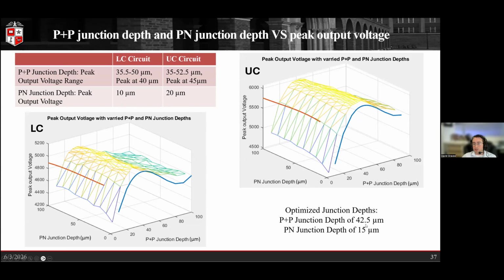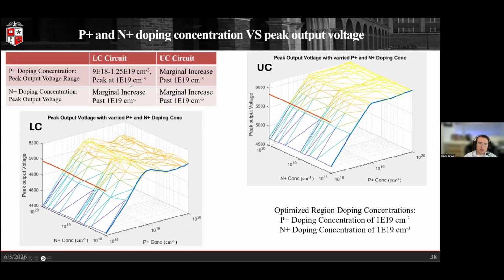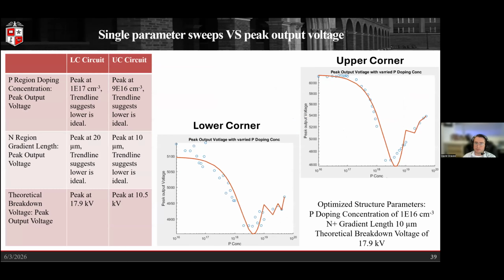Looking now at the P plus P and N plus doping concentrations, again optimizing around that peak output voltage, as that's one of the primary metrics for these devices. We found a peak at 1E19, and we found marginal increases in the upper corner circuit once it went past 1E19. And again, we saw marginal increases in both circuits for the N plus doping concentration past 1E19. And that helps from the manufacturing standpoint, not having to hit that high solubility limit of silicon carbide, particularly for our substrate. And so we ended up picking 1E19 as our ideal doping concentrations for those regions.